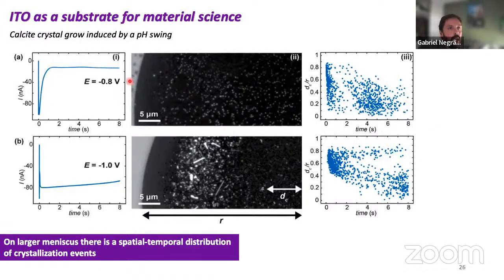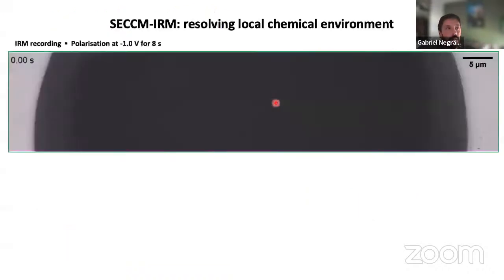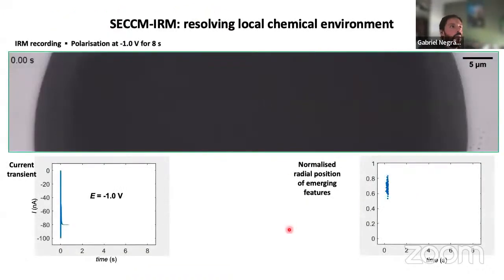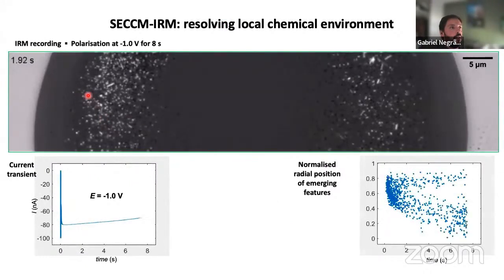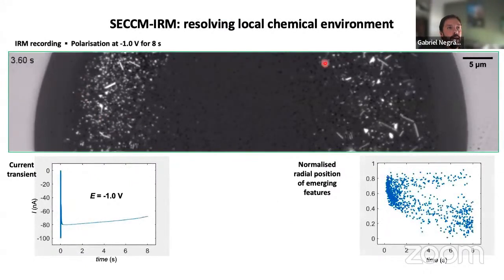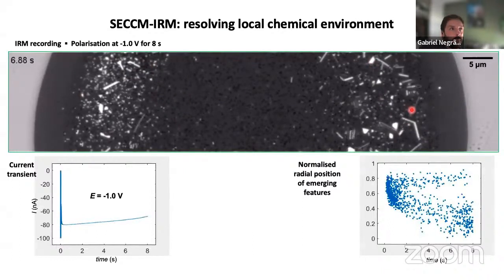And we try to see how crystallization happened, if there's any spatial distribution. And just from those snapshots, I can clearly show you guys there's a different spatial distribution, of course, at different potentials and different timeframes. But I think if I show you the videos it's a little bit nicer. So we're applying a potential here to reduce oxygen. So we're swinging the pH, and you can see at first, not much happens. No, sorry, I think I have to plug it. So things happen at first mostly at the edges, and then the entire surface is covered, and at the edges I have larger crystals forming, right?